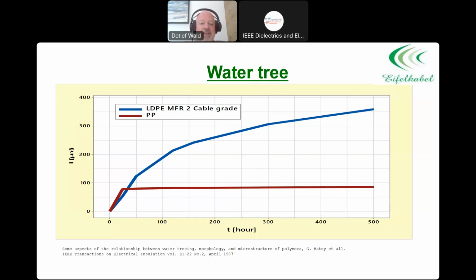Speaking of another thing about contamination, there are comparisons done on water treeing, which is known, since contaminations can create water trees under certain tests. So here's a comparison done of polypropylene with an LDPE cable grade. As you can see, it's not that new. It was published in 1987, so that was before I started working in the cable industry. And polypropylene there is better than polyethylene in this specific test.